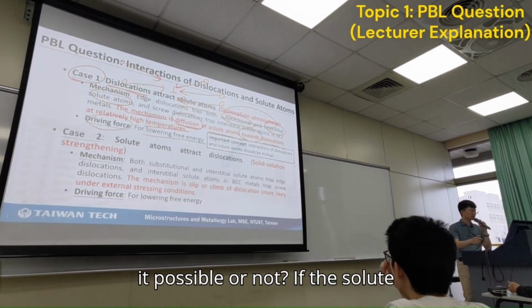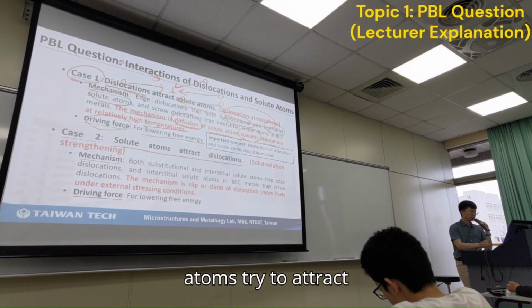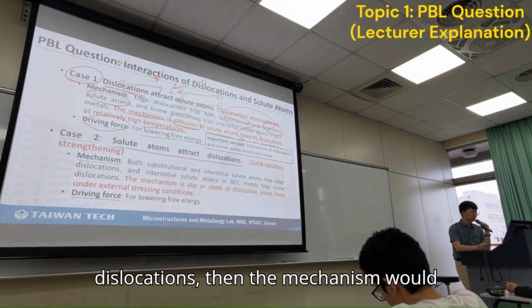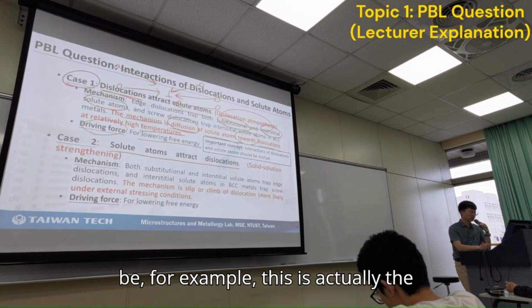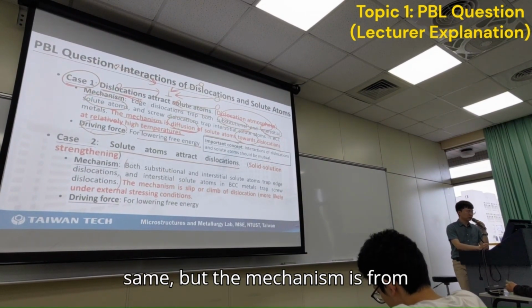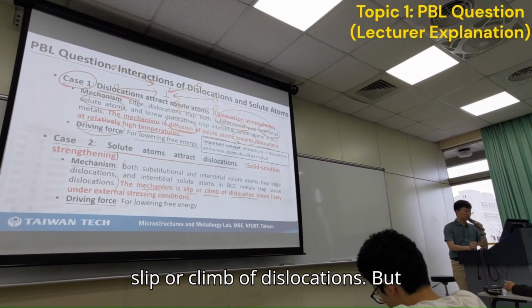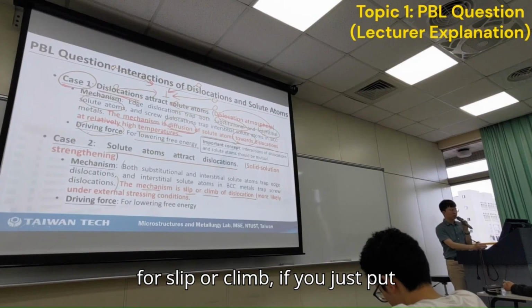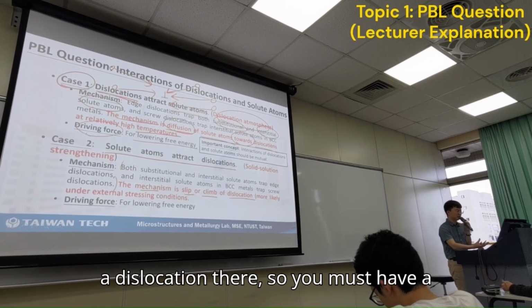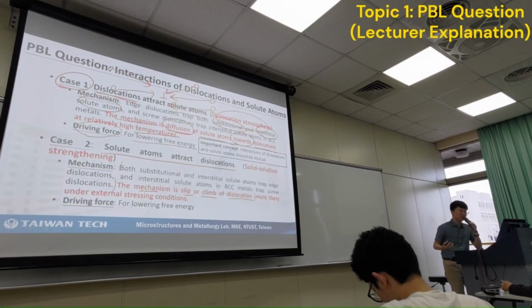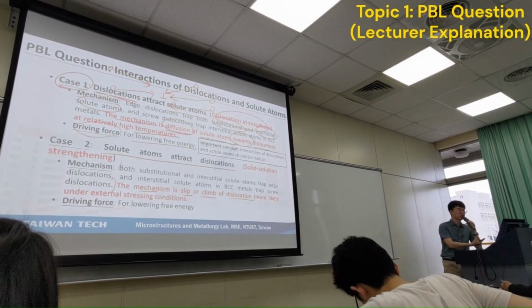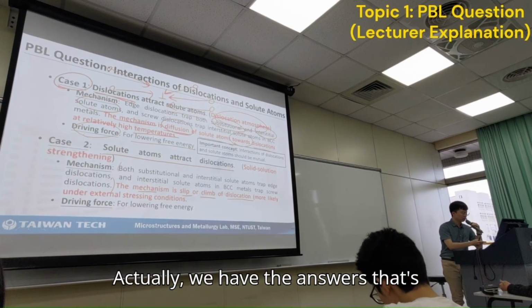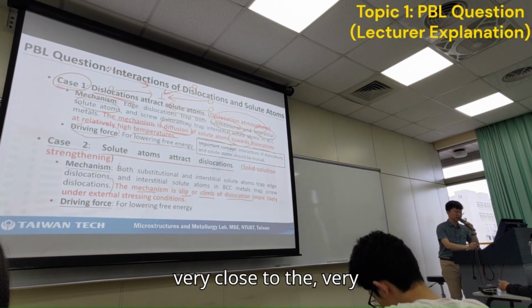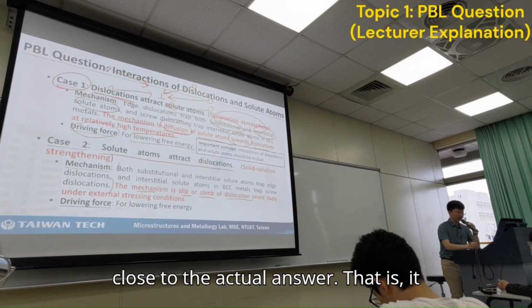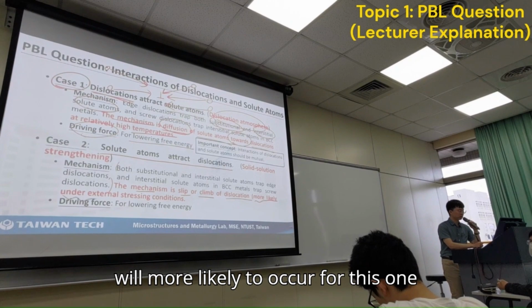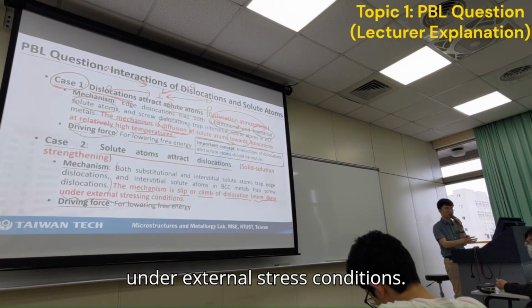How about case 2? Is it possible or not? If the solute atoms try to attract dislocations, then the mechanism is the slip or climb of dislocations. But for slip or climb, if you just put a dislocation there, you must have a very strong motivation for that dislocation to move. So we have an answer that's very close to the actual answer: it is more likely to occur under external stress conditions.